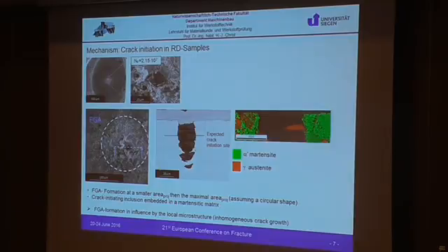Let's take a closer look at the mechanisms. We see here the fracture surface of the RD sample, and we obtained metallographic sections through the middle of this inclusion, and I show it here. The applied stress is in this direction. This would be here the crack surface.